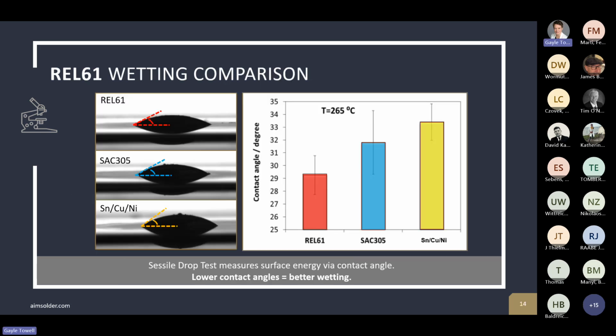Here we have a wetting comparison. So this was the sessile drop test. It measures basically, you can look at the angle of contact of the drop of molten solder. Lower angle tends to indicate better wetting performance. And if we compare the angles between REL61, SAC305, and the tin copper nickel alloy, we have a lower contact angle with REL61, indicating slightly better wetting compared to the other alloys.